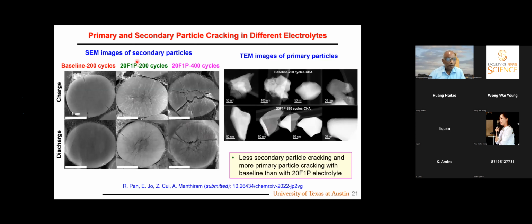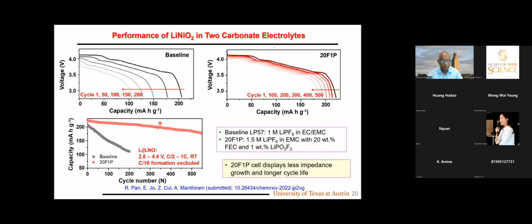So these are the SEM images of the secondary particles, LP57. After 200 cycles, maybe a little bit of crack, but we don't see too much. The other electrolyte already at 200 cycles, you see some secondary particle crack. If you go to 400 cycles, a lot of secondary particle crack, but it is surprising. This has crack, but if you look at the cyclability, it is exactly the opposite.